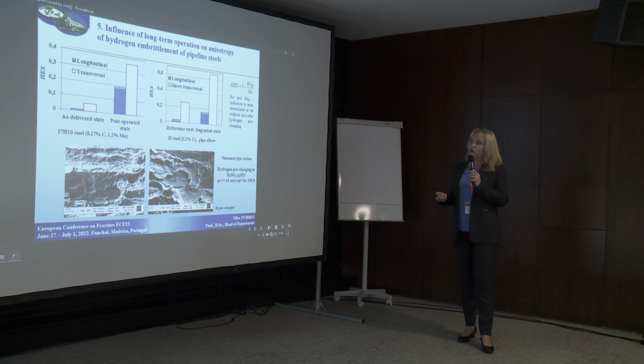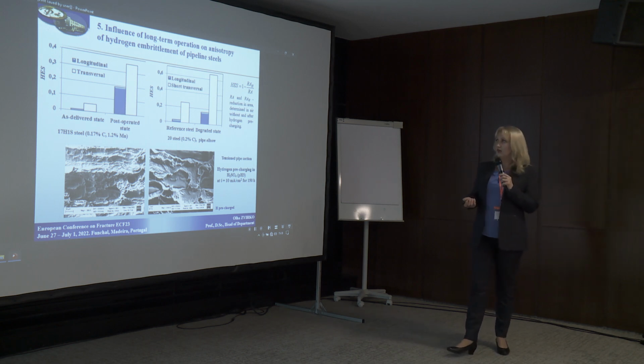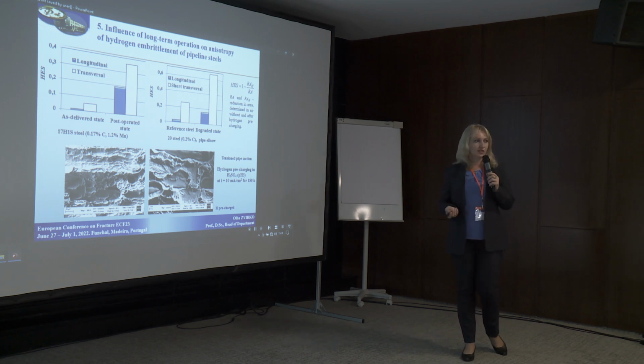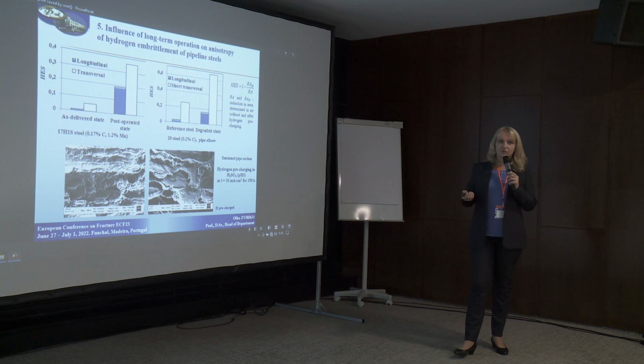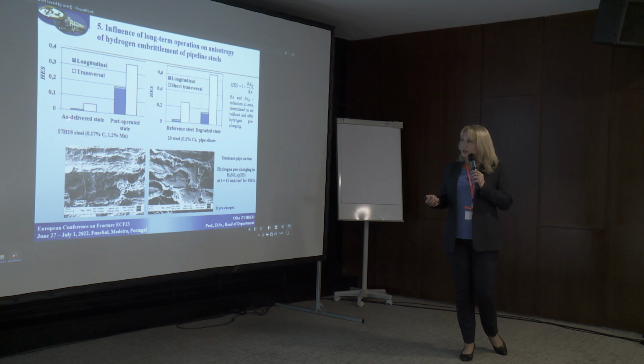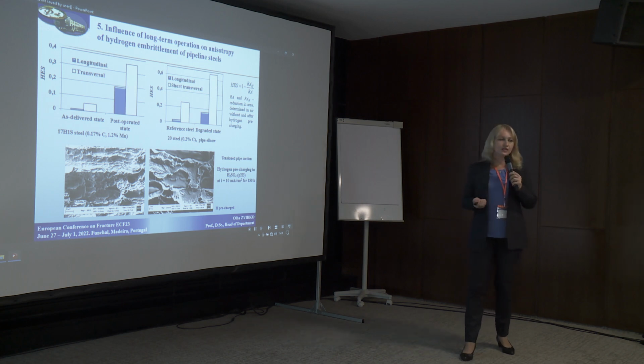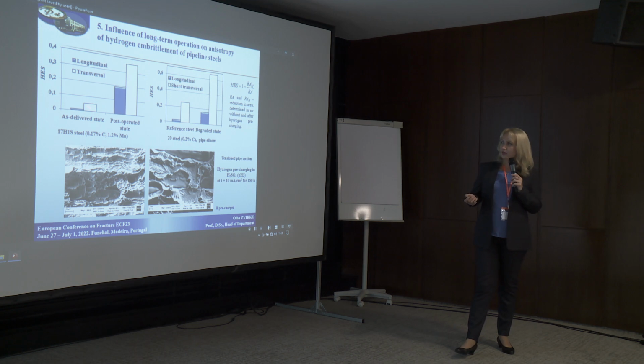Here presented data show sensitivity of pipeline steels to hydrogen embrittlement depending on their degradation degree and also orientation of the specimens cut out relative to the rolling direction of the pipe. And hydrogen embrittlement susceptibility was estimated by changes in reduction in area due to preliminary hydrogen charging. So as we can see, the as-delivered state and also reference steel aren't sensitive to hydrogen embrittlement when testing longitudinal specimens. However, they become sensitive to hydrogen embrittlement when testing transversal and especially short transversal specimens.